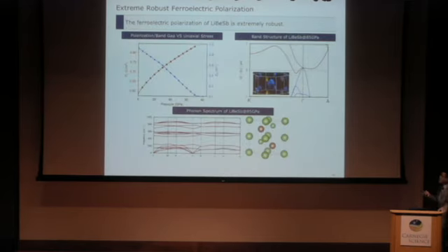This is the last slide. It turns out that for some ABC ferroelectrics, the polarization is extremely robust. What I show here is the polarization as a function of hydrostatic pressure all the way up to 80 gigapascal. And the red line is the polarization. As you can see, it keeps increasing. Around 80 gigapascal, the band gap closes. So beyond that, because the structure is metallic, we cannot define the polarization.